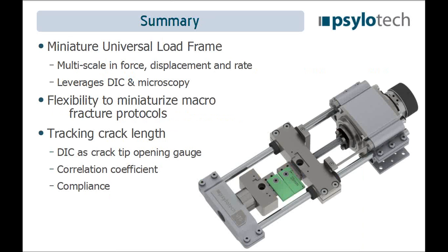This is my last slide. I appreciate your time. To summarize, we have this miniature universal load frame. It's meant to enable all kinds of different experiments at multiple scales in force, displacement and rate. It can go very fast and very slow because of the servo-controlled ball screw actuator. It doesn't have a gearbox, so it's quite fast. It has a large stroke. You can get down to 2-3 nanometer closed-loop control on some of these systems, and the stroke is 40 millimeters, so you're talking about 6 orders of magnitude of displacements.